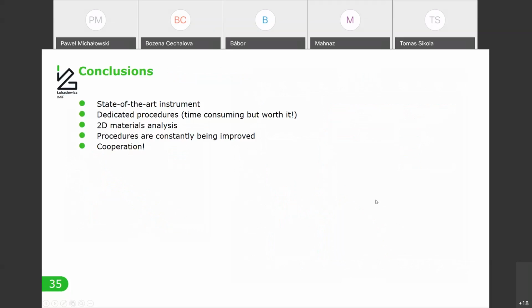Okay, so just a short conclusion about my talk. I showed you, well, I can say a state-of-the-art instrument, which allows to use very low impact energy and manipulate the incident angle, combined with the dedicated procedures that I try to develop, which are very time-consuming, but as you can see, worth it. It is indeed possible to analyze 2D materials and also other materials with very good resolution, very often sub-nanometer depth resolutions.